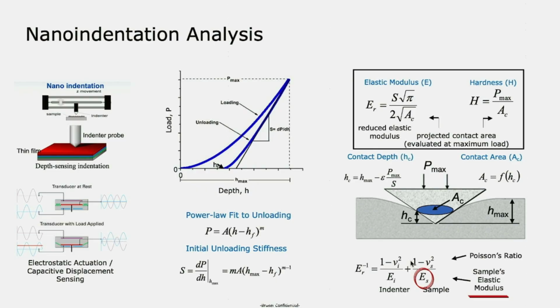This is the maximum force divided by the projected contact area. So the difference between nanoindentation and the Vickers indenter is that we can tell the customer the elastic behavior, just like Young's modulus. We can tell the customer hardness as well. And why is this in nanoscale? Because the transducer must be very accurate. The displacement is accurate to below nanometer accuracy. Also, the force has very high resolution, accurate to about nano-Newton resolution. So everything we are looking at here is on the nano and micro scale.